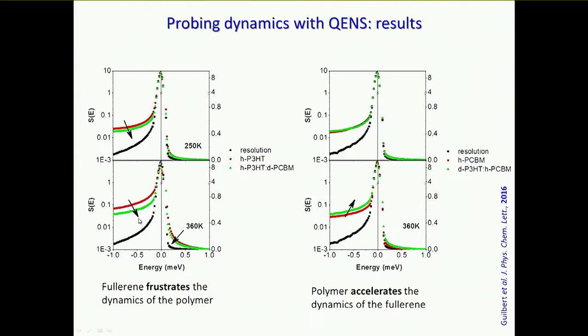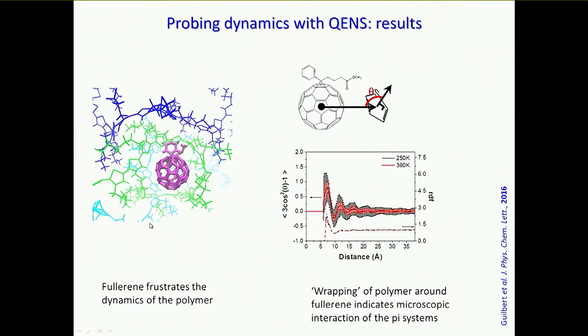With the MD, we could reproduce the QENS results. I don't show that here, but I want to show a nice result from the MD. When we look in detail, we found there seemed to be a specific molecular interaction between the fullerene and the polymer, in such a way that the fullerene tends to bring the thiophenes into a cofacial arrangement, where the first layer of polymer outside the fullerene shell is more likely to be organized in a cofacial manner relative to the fullerene.